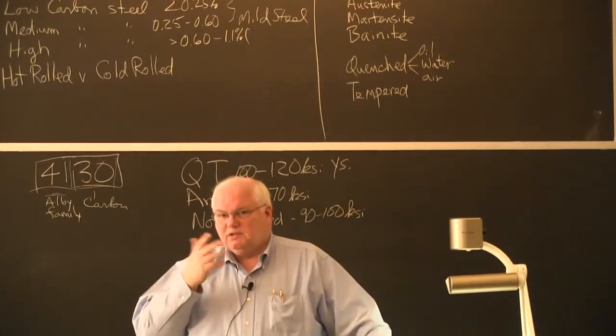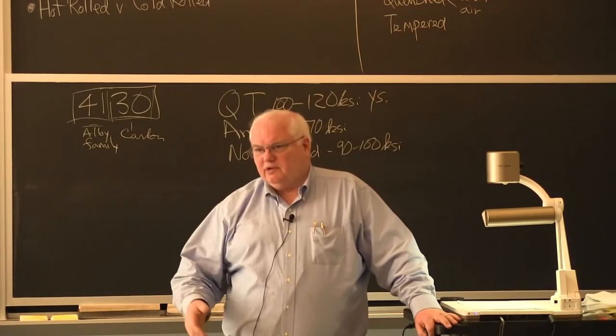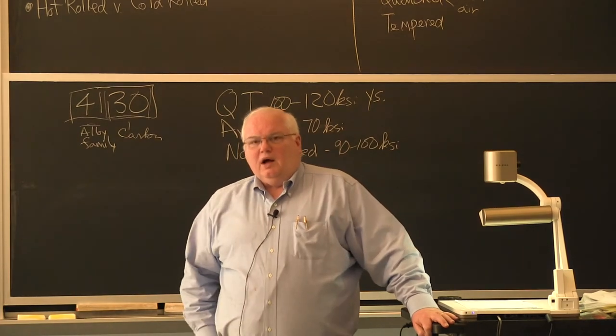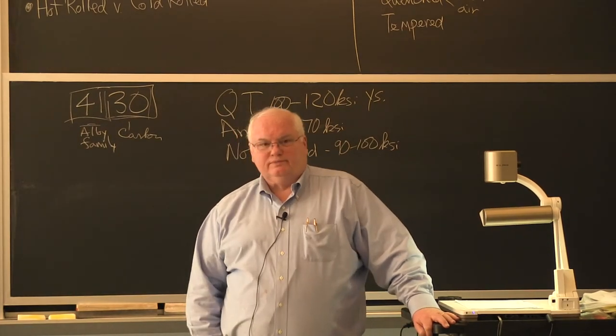But basically, annealing, you're trying to get what we call a dead soft material. Normalized, you're trying to get a fine grain size. The purpose of the heat treatment is different. And you adjust your heating temperature and your cooling time in normalizing to get fine grain size. And annealing, you don't worry as much about the grain size. You're looking for softness, okay? And so they have different names.